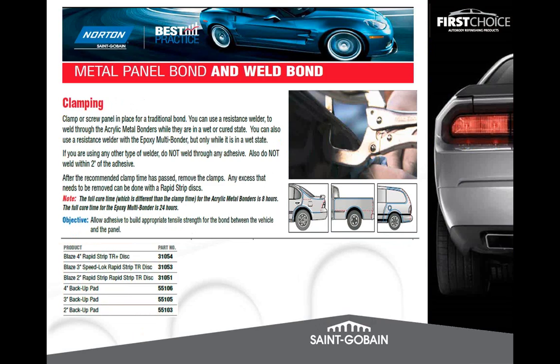The advantage of an acrylic, it can be either wet or dry, but you can also only do resistance spot welding with an epoxy when it's in its wet state. Okay, and you'll also notice that if you're using any other type of welder, specifically maybe a MIG welder, then you don't want to get within 2 inches of the adhesive. As I mentioned, the epoxy will catch on fire. The acrylic, if it's too powerful, you could burn away the acrylic, but most resistant spot welders will be just fine.